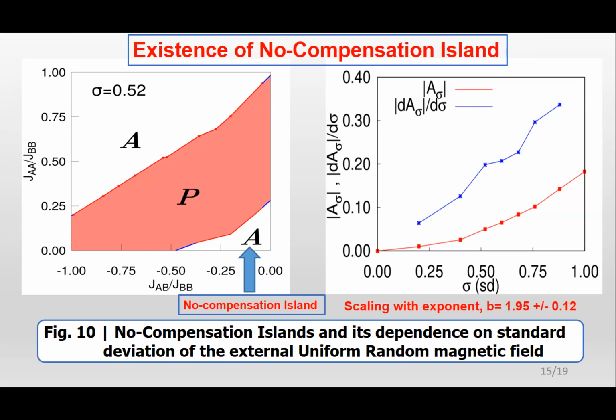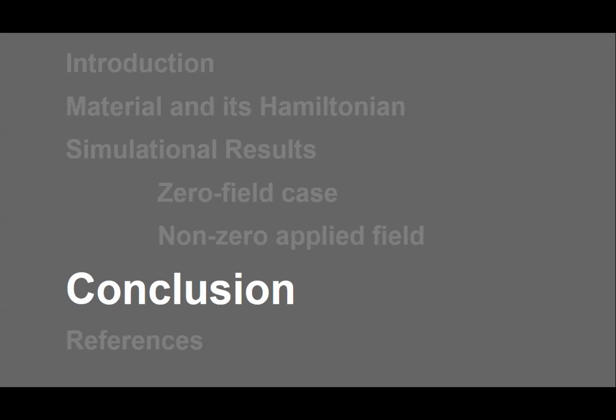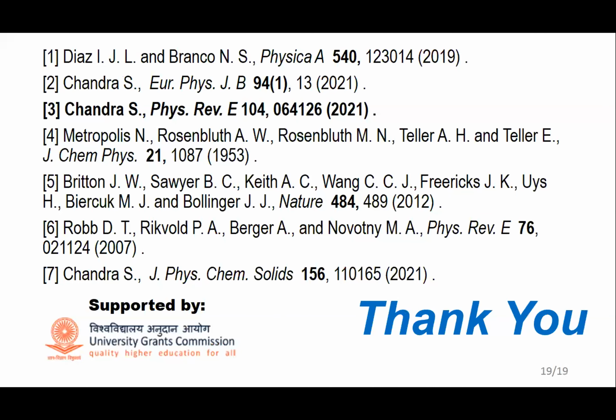So we find that basically a scaling of the area of no compensation islands exists with a scaling exponent of 1.95 plus minus 0.12. So with this, I would like to conclude right now.